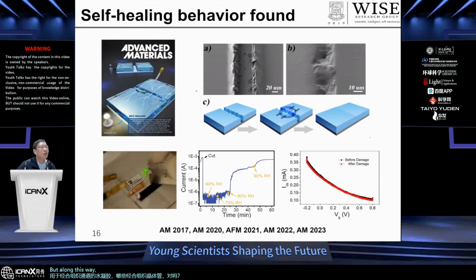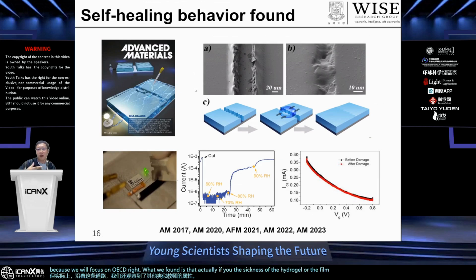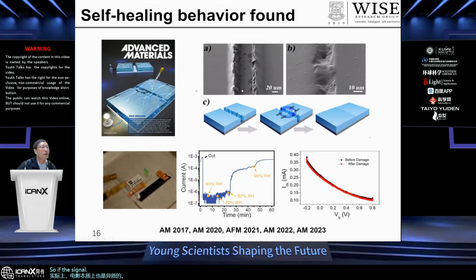But along this way, we also observed other tissue-like properties because we focus on OECT, right? What we found is that the thickness of the hydrogel or the film is hard to define, because a thin film by nature is also a hydrogel. If the thickness is about 1 micrometer, which is not thick, it still maintains a semiconducting film. Then as long as a water droplet touches the gap, it can heal automatically. Or even if it's not a water droplet, but humidity. For example, we change the ambient humidity from 60 to 90, then it can heal the current.